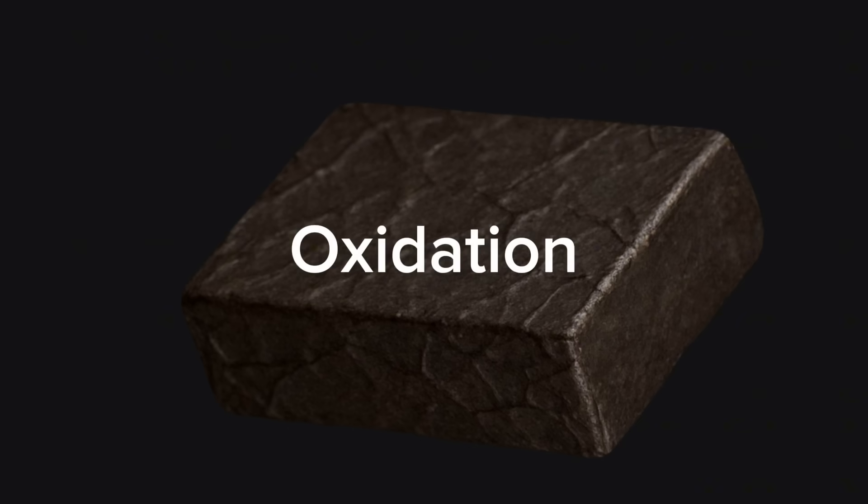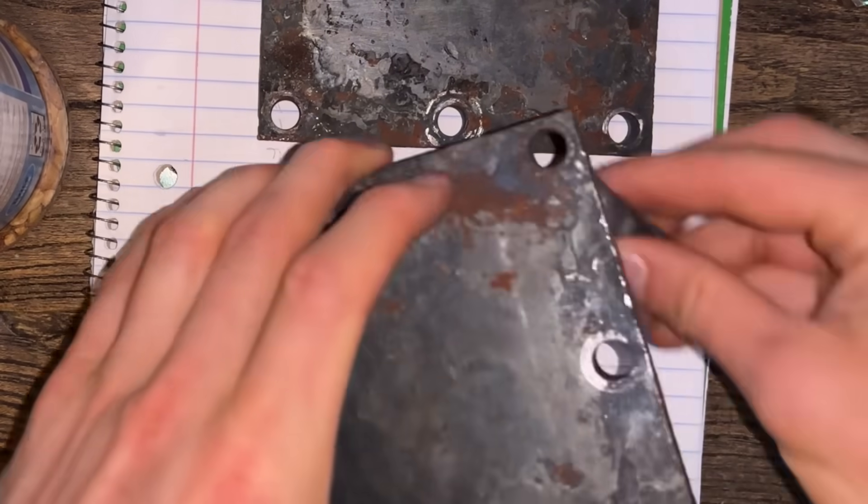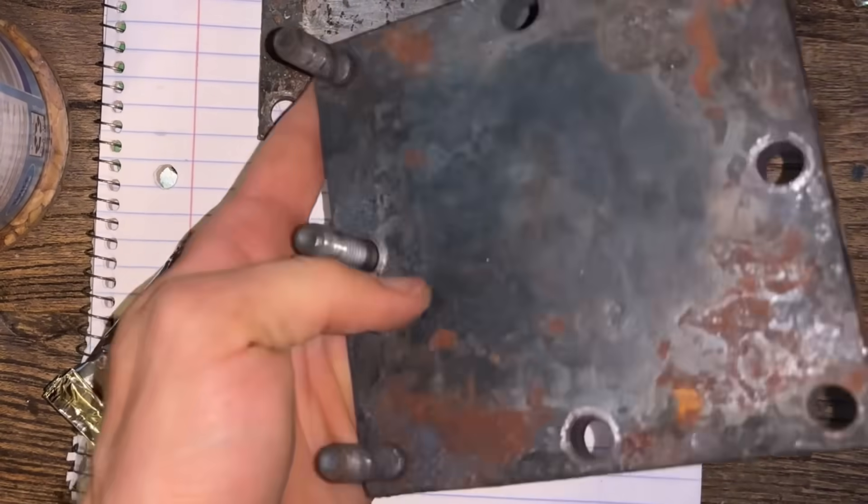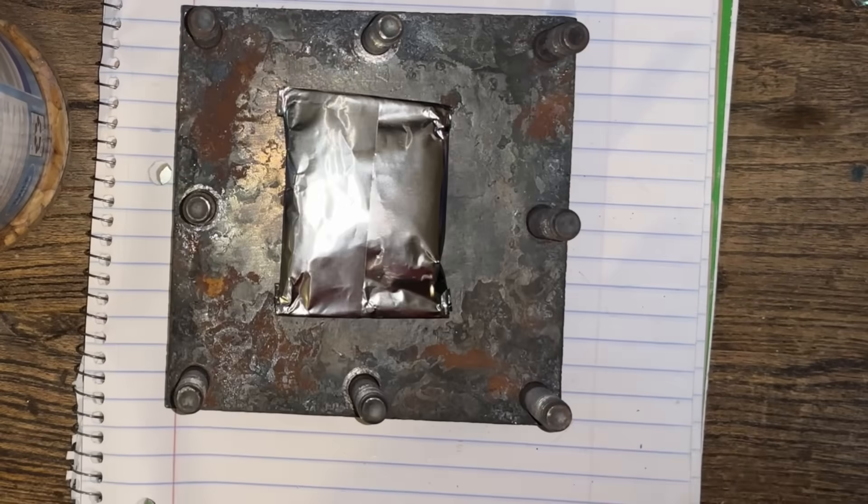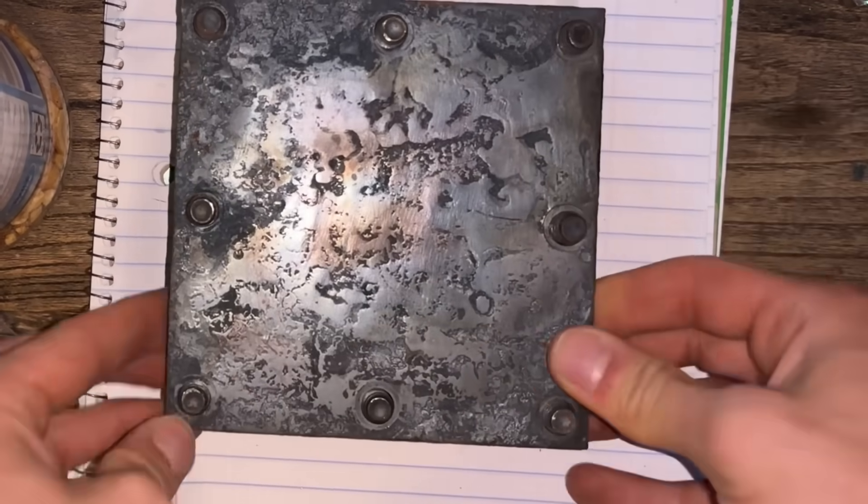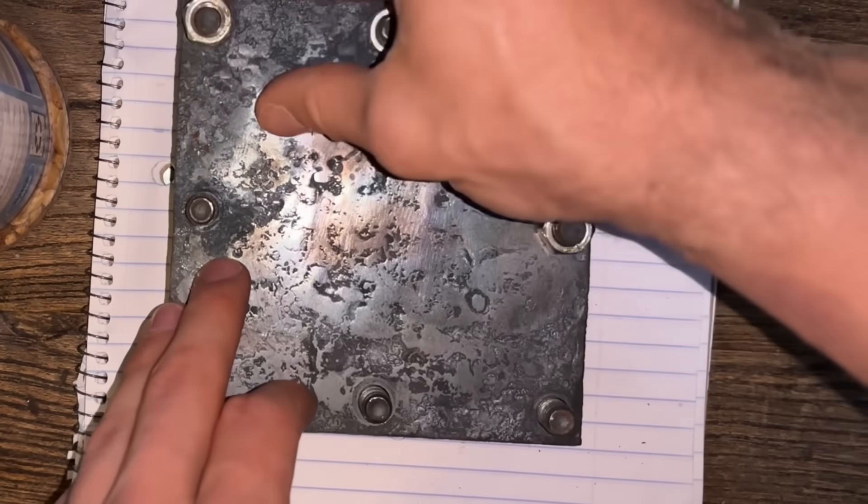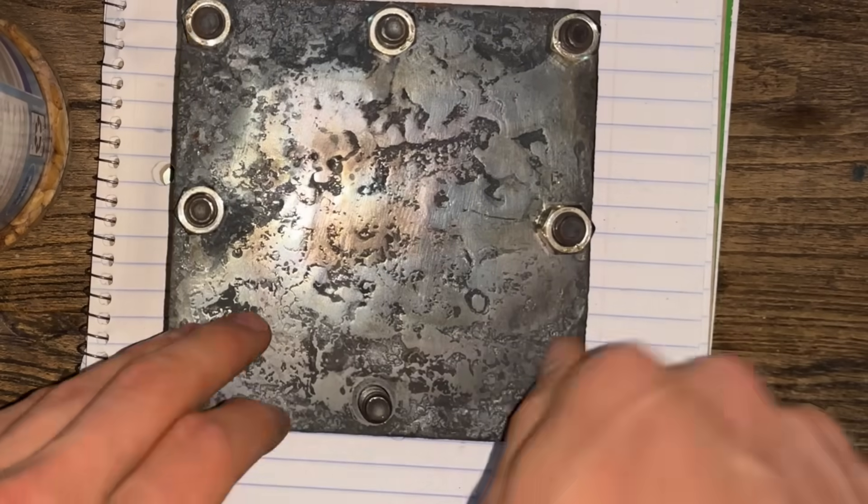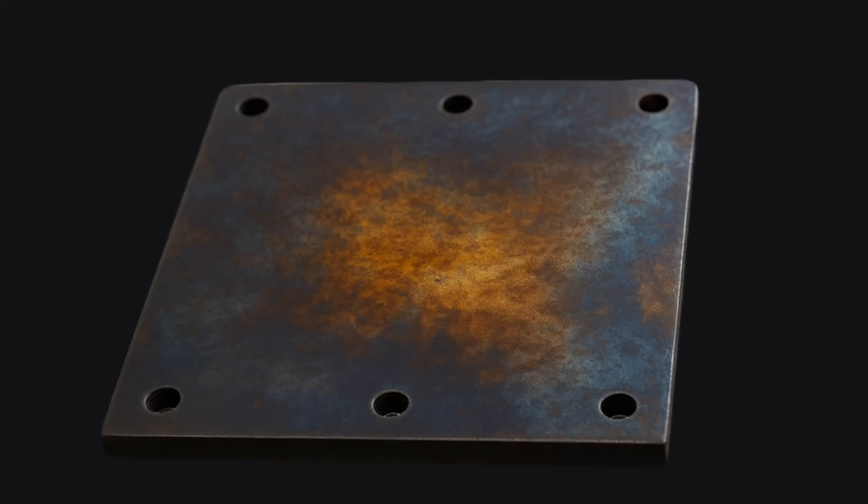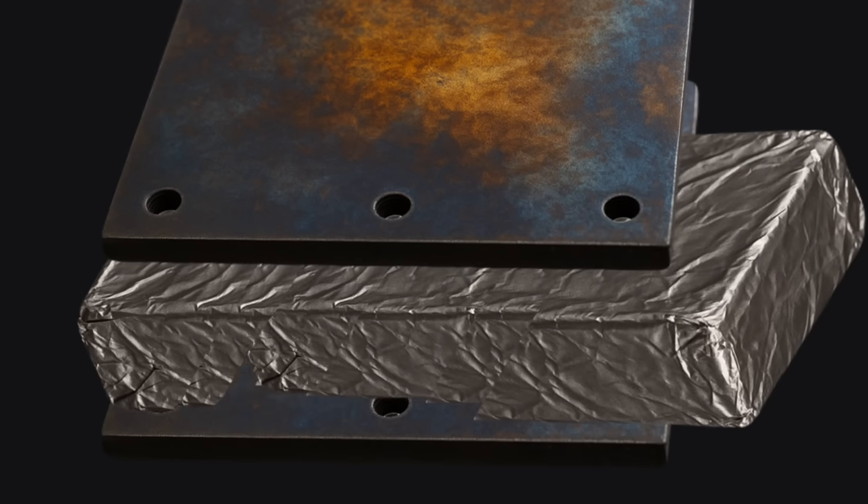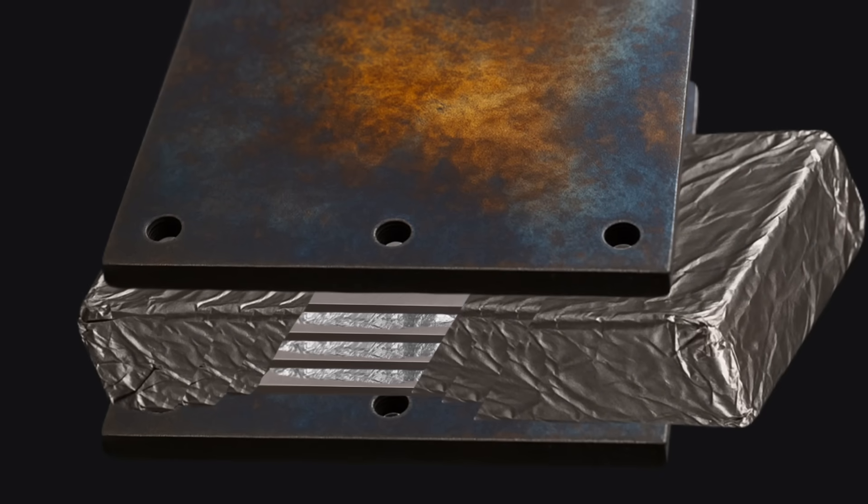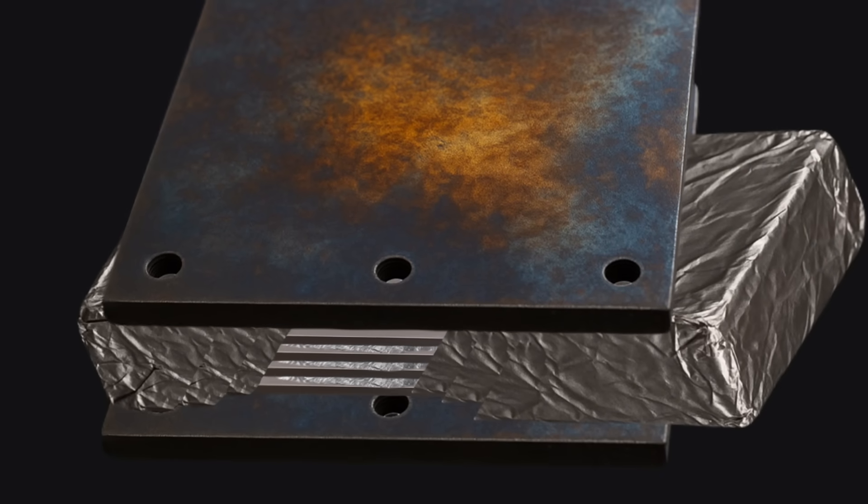My plan to prevent oxidation at high temperatures is to do this entire reaction under high pressures. And the approach to that is really quite simple. I have two steel plates with fastener holes drilled all throughout the edges. I'll sandwich my stack up between these two steel plates and torque down fasteners in order to put the stack up under pressure. This high pressure will remove any air from between the layers, thus reducing the oxidation where it really counts.